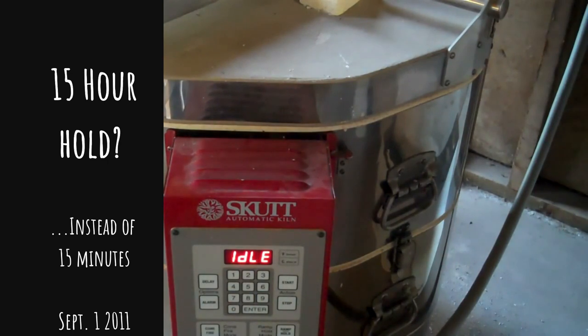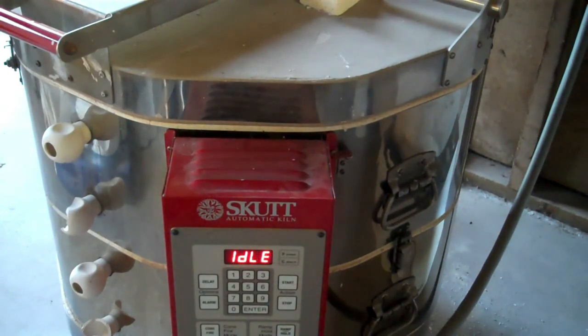Let me explain what happened with this kiln load. I had set it for cone 5 with a hold time of 15 minutes — at least that's what I thought. When you enter 15 minutes on a kiln it's actually entered as '1-5-0-0,' not like 15 minutes on a microwave. Thanks to Tim C for bringing that to my attention, because that's exactly what happened. I caught it when I still had six hours to go on the 15-hour program — it had been holding at 2,100 to 2,167 degrees for nine hours when it should have only been 15 minutes.